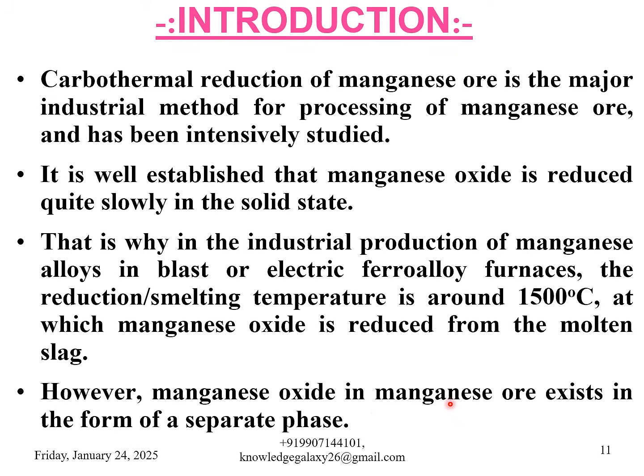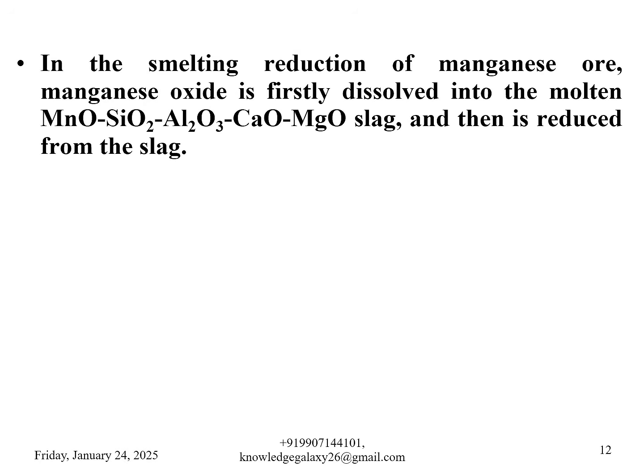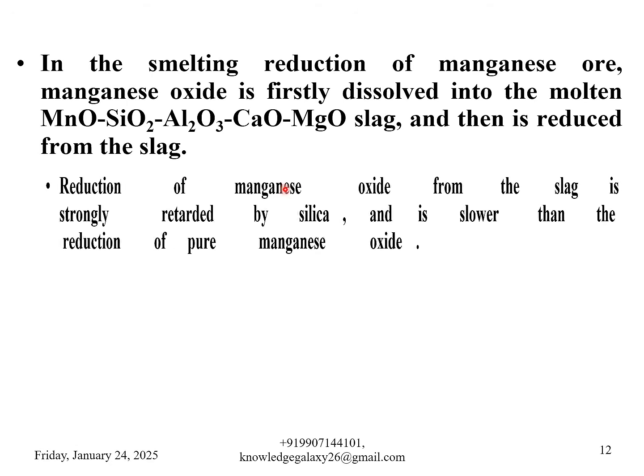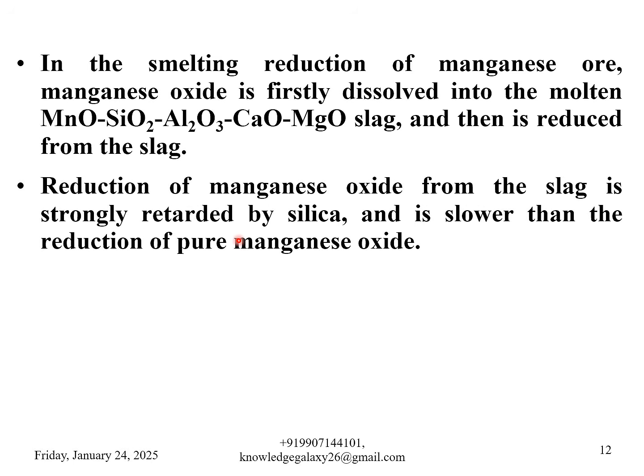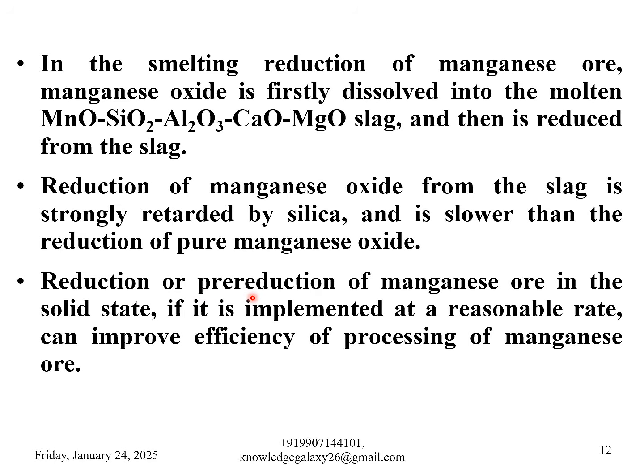However, manganese oxide in manganese ore exists in the form of a separate phase. In the smelting reduction of manganese ore, manganese oxide is firstly dissolved into the molten MnO, SiO2, Al2O3, CaO, MgO slag and then is reduced from the slag. Reduction of manganese oxide from the slag is strongly retarded by silica and is slower than the reduction of pure manganese oxide. Reduction or pre-reduction of manganese ore in the solid state, if it is implemented at a reasonable rate, can improve efficiency of processing of manganese ore.